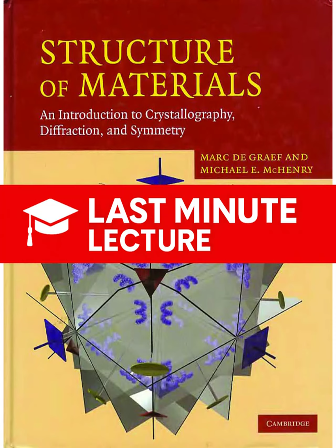Rule 1 deals with the coordination polyhedron and the radius ratio. Okay, the radius ratio. The rule dictates stability based on the radius ratio, cation radius over anion radius. For silicon and oxygen coordination, the theoretical ideal critical radius ratio for perfect tetrahedral coordination is 0.225. But the calculated ratio is a little different. It's slightly smaller, 0.167. So the silicon atom is a bit smaller than ideal for that perfect fit. What's the structural implication of that mismatch?